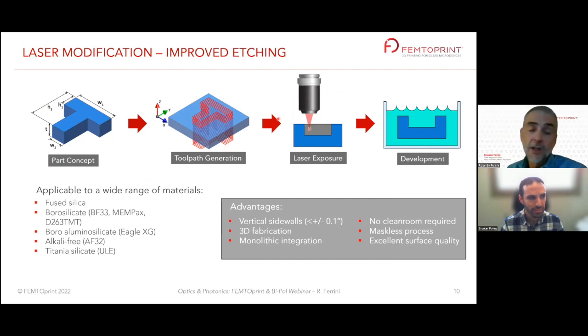It's an infrared laser. Normally, if you shine a femtosecond laser through glass, nothing happens. But if you focus the laser very strongly, you create what we call a voxel. A voxel is an ellipsoid, which is typically 3-4 microns wide and up to 10 microns high. And you have the entire power concentrated in this tiny voxel, which is our pencil.